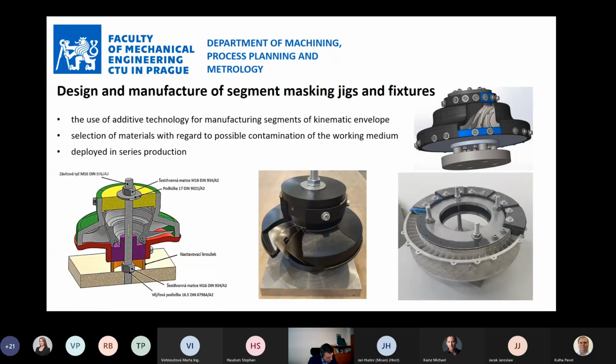Regarding inspection, we don't have to finish with the inspection, but as I mentioned, we have some experience with special finishing technologies. We have developed for another aerospace company a technology for polishing components, and a few of those were also 3D printed. So this is some stage of development of the polishing technology, where, because these parts are quite expensive, when you want to test more process parameters, you have to be able to cover part of the workpiece to use it maybe 10 times for different production parameters. So we have designed several, again, additively manufactured masking fixtures. Then from one part, we can do, for example, 20 process parameters. We can test them and we can optimize the process.